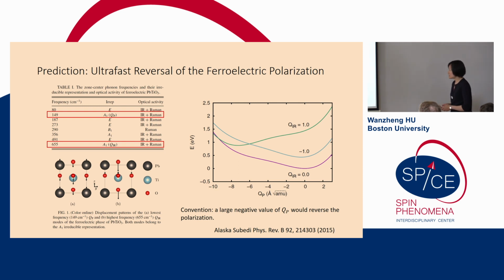This is initiated by Alaska Subedi's prediction. He studied lead titanate, and he found there's a strong Q_IR squared Q_R coupling that you saw in Nicole's talk this morning. Basically, this high energy IR mode couples strongly to the low energy ferroelectric mode. And by driving the high energy IR mode, Alaska predicted there can be an ultrafast ferroelectric switching, which is also long-lasting. The result is shown here.